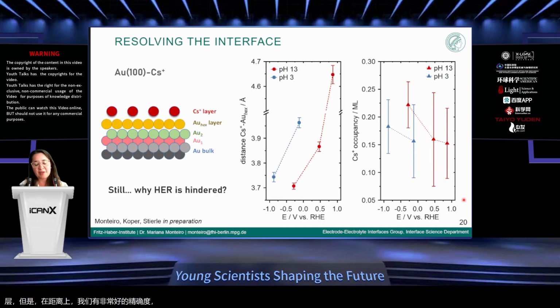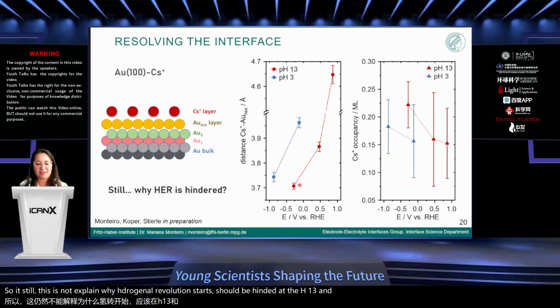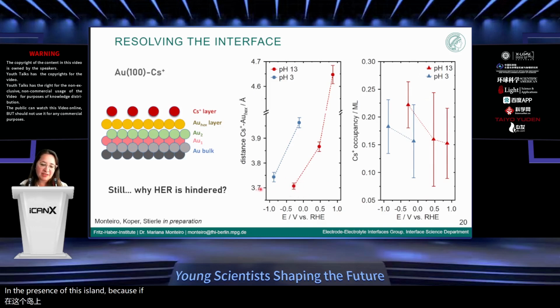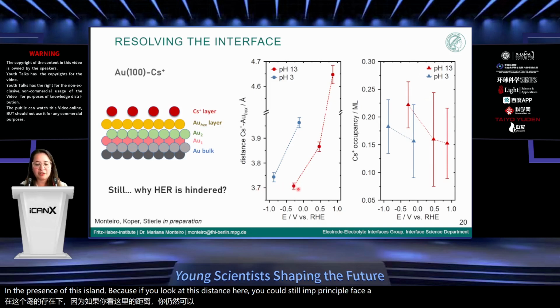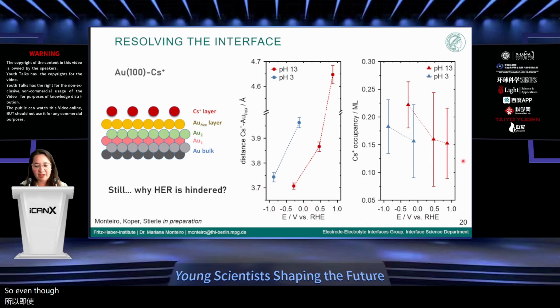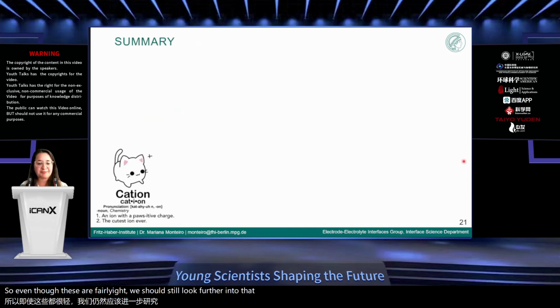So still, this does not explain why hydrogen evolution starts to be hindered at pH 13 and above in the presence of these ions, because if you look at this distance here, you could still in principle fit a water molecule here in between. So even though these are valuable insights, we should still look further into that.